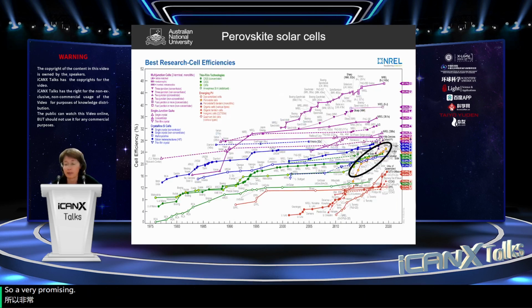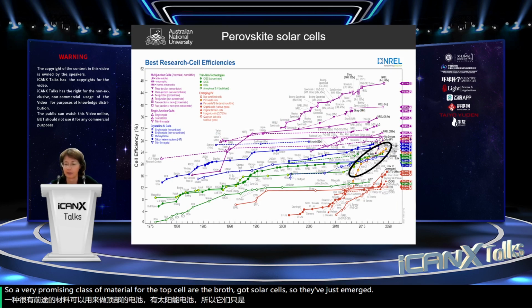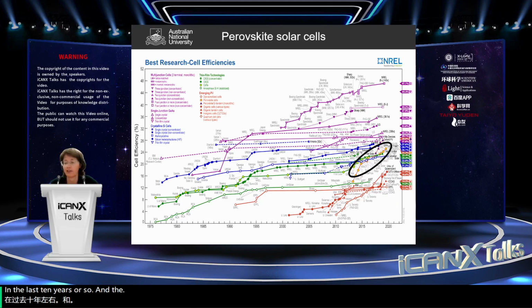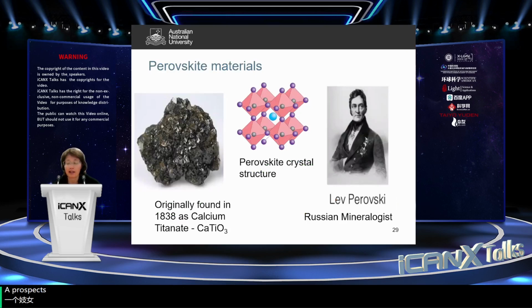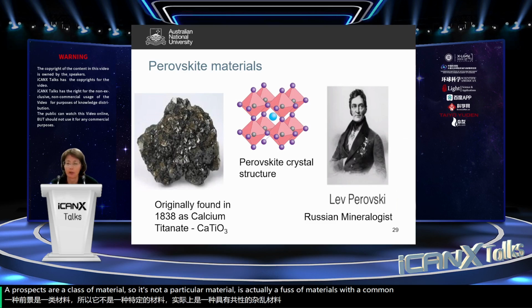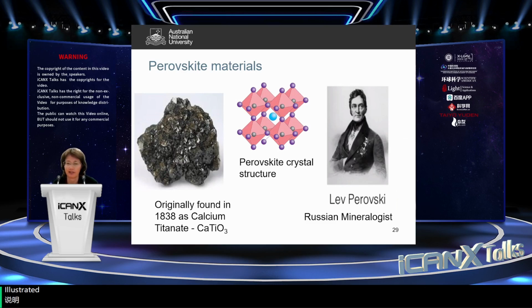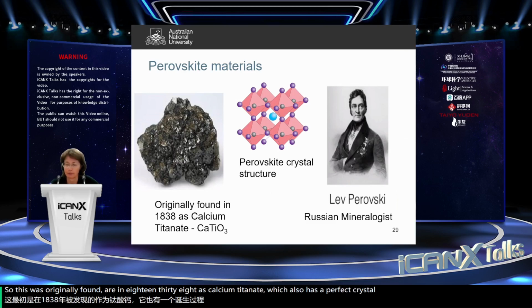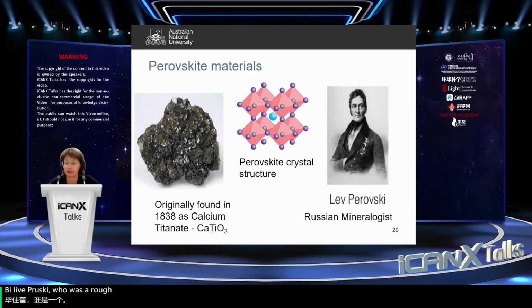So a very promising class of material for the top cell are the perovskite solar cells. They've just emerged in the last 10 years or so, and you can see that the cell efficiency has climbed very rapidly for perovskite solar cells. Perovskites are a class of materials, so it's not a particular material, it's actually a class of materials with a common crystal structure. That's illustrated there. You can see the classic octahedral crystal structure there. This was originally found in 1838 as calcium titanate, which also has a perovskite crystal structure, by Lev Perovsky, who was a Russian mineralogist.